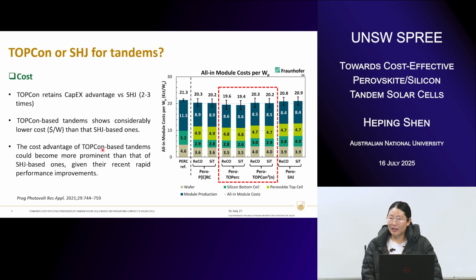So this is a techno-economic analysis done a few years ago by Fraunhofer, comparing the tandem cost based on different bottom silicon cell technologies. As you can see, we have PERC technology, TOPCon and double-sided TOPCon, as well as silicon heterojunction. That cost takes into consideration both the efficiency potential as well as the realistic industrial manufacturing cost. It indicates that the tandems based on TOPCon cell structure, either the one-side TOPCon or the double-sided TOPCon, show considerably lower cost, dollar per watt, compared to those based on silicon heterojunction.